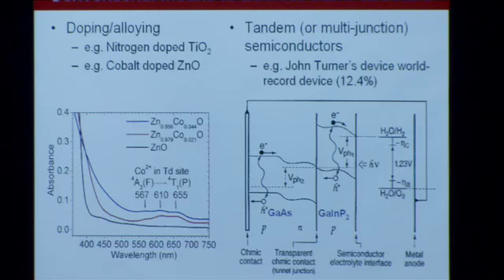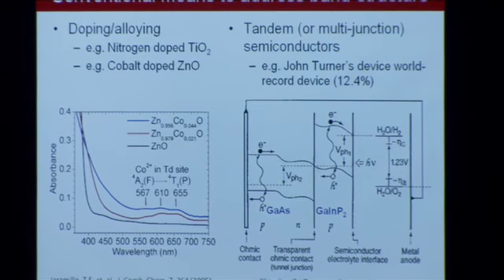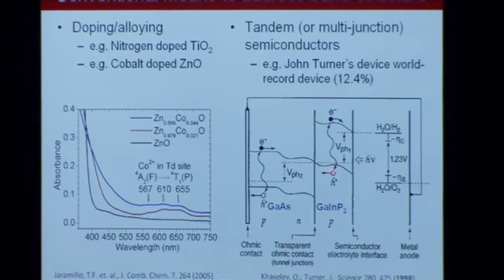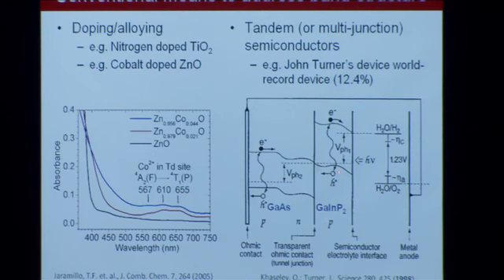That gallium arsenide effectively gives it a photovoltage boost, so that this hole no longer has to oxidize water to oxygen. Now that hole combines with a photogenerated electron from the gallium arsenide. So you lose that efficiency. You take an efficiency hit there because you're recombining your electron and hole, but now you can use this hole on your counter electrode to oxidize water. So that's another approach that one can take.